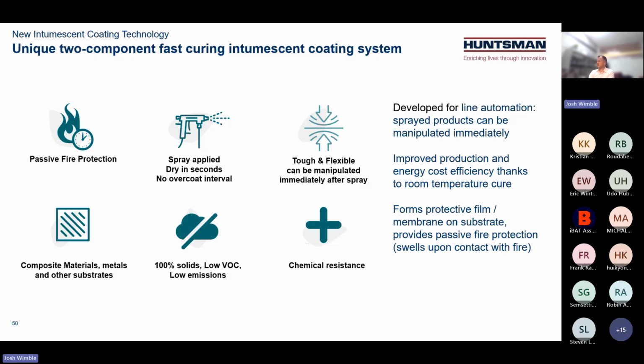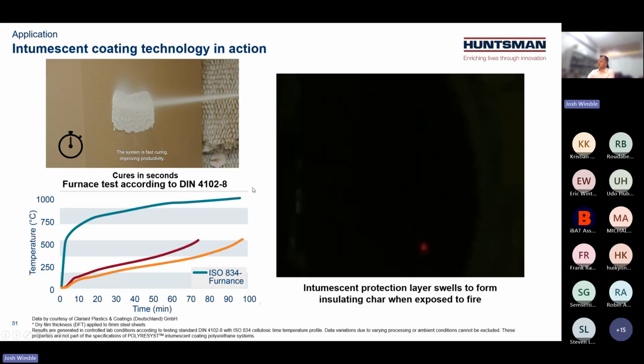Huntsman already has a fast curing intumescent coating system that's found success in some other markets that are extremely sensitive to flame. I won't go into a lot of detail about this. If it's something you'd like to talk about, please follow up with us. But this is a technology that can be sprayed onto just about any composite surface and pre-treated metal surfaces, has 100% solids, very low VOC, low emissions. It's a very tough and flexible system that is designed to be sprayed on and provide really intense thermal protection.